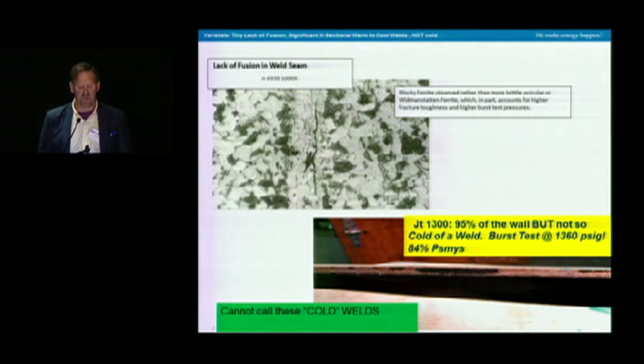But a lot of what we got out here in this pipe, even though it's not post-weld heat treated, is this blocky ferrite, which is probably giving us, as you're going to see in these burst test tables in a few minutes, this higher fracture toughness, and allows us to assume a little higher than 4 foot-pounds in the long seam. And I think the data shows that with the burst testing. As a side note, what you'd expect to see in some of this non-post-weld heat-treated area right here in the long seam is this more brittle acicular, or, for the Germans in the audience, the Widmanstätten ferrite. So that blocky ferrite really is what's giving you the properties.